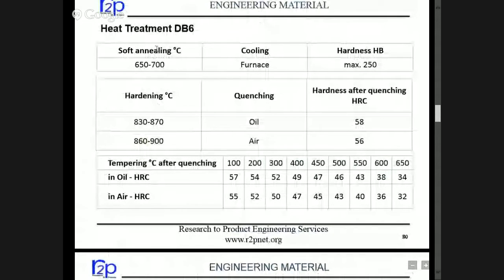The temperature for annealing is 650 to 700, then cool in the furnace, and for hardening 830 to 870, quenching in oil or air, and hardness after quenching is 58 to 56. Again, tempering we have to do. The tempering temperature defines the ultimate hardness you achieve on the die.